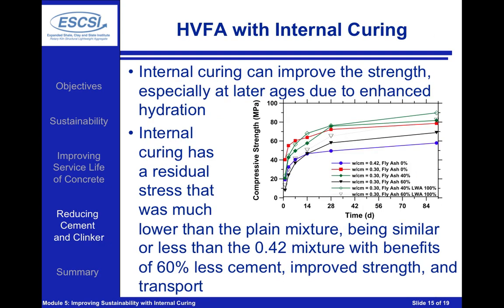Now, the open symbols are going to be our internally cured mixtures, and the real takeaway from this is internal curing has the ability to provide us very similar, if not slightly higher strengths than what we see in our conventional systems. So we're providing a system that now is going to provide more water to hydrate the fly ash, more water to hydrate slag, but providing an overall similar compressive strength to what we see in our conventional system. In addition, by supplying the internal curing water, we can dramatically reduce the potential for shrinkage and cracking.